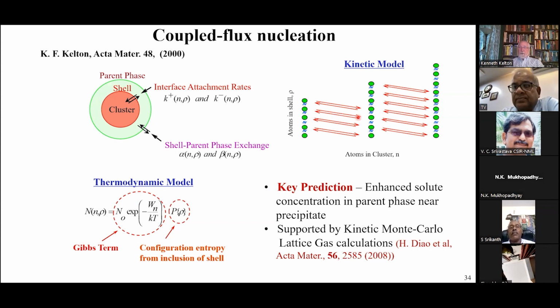You can solve this model with computer calculations, and one prediction is that you end up getting an enhanced solute concentration in the parent phase near the precipitate, if you're thinking about single component precipitation. That's contrary to what we normally think of in growth, where you would see that there's a depression of the solute concentration next to the growing precipitate. But this is nucleation, not growth. Nucleation, since it's stochastic, you can have fluxes coming from the cluster into the shell and from the parent phase into the shell, and they're all coupled. And this observation from the computer calculations that I did has been supported by kinetic Monte Carlo calculations.